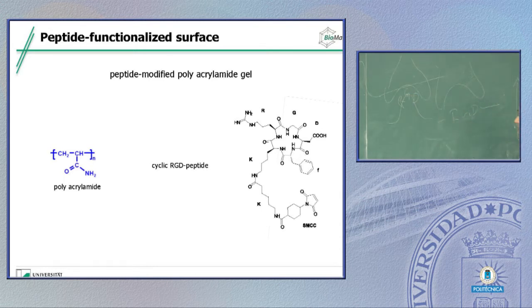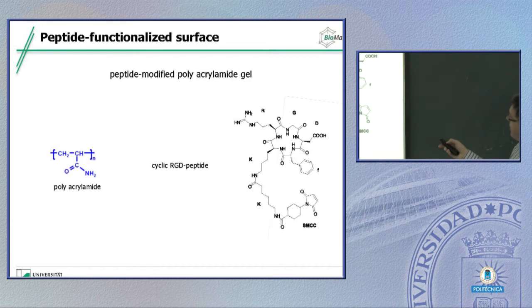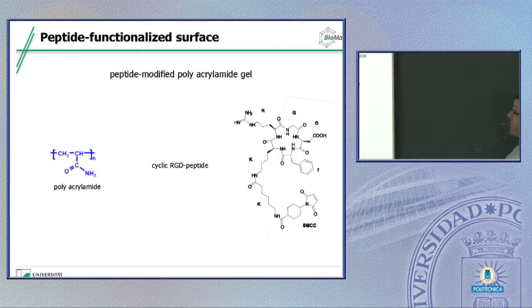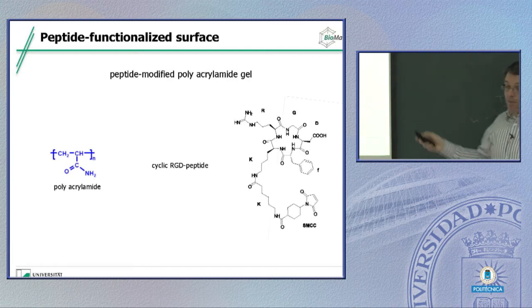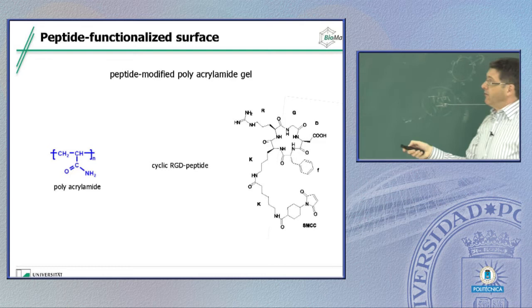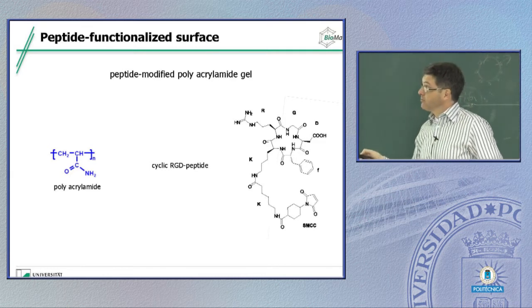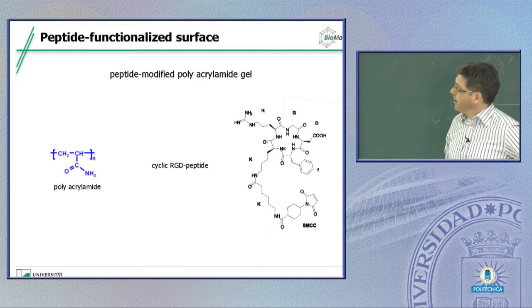And for that reason, researchers actually developed something like a cyclic peptide. So here you see the R, the G, and the D, and they're actually circularized, and you can do that by chemical synthesis. That works quite nicely. And here you're now somewhat mimicking this turn-like structure. So therefore, people typically use cyclic RGD. And cyclic RGD peptides work much better in combination with the polymers.